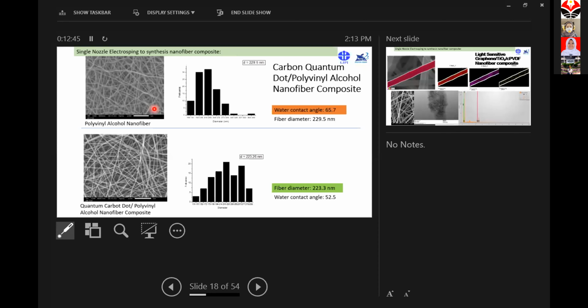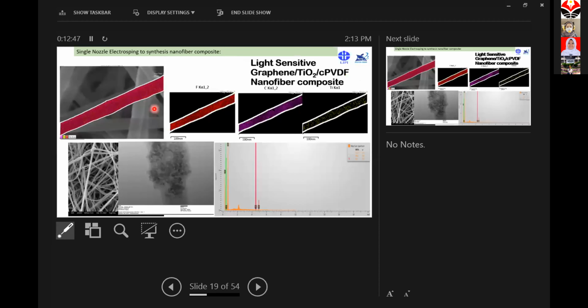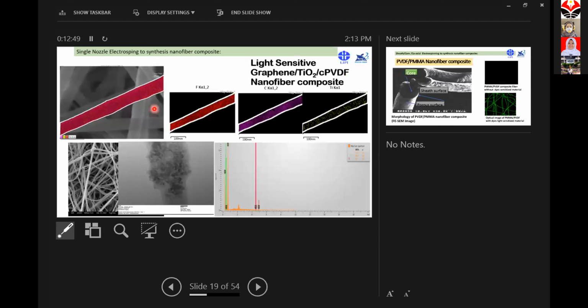This is an example. Also, by using single nozzle electrospinning, we can make light sensitive graphene, titanium dioxide, co-PVDF nanofiber composite. You can see here we can combine two nanomaterials, graphene and titanium dioxide. We make a polymer solution by using PVDF, and then we use organic solvent and mix it, and then we can make this nanofiber composite.